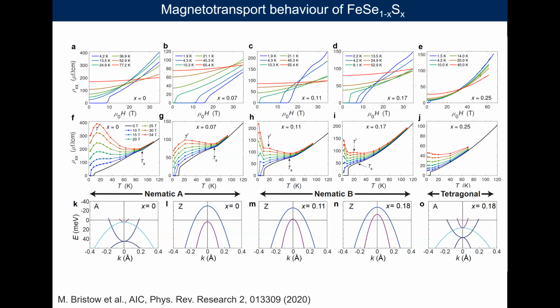So this system should be in the normal state by now. You know, we are measuring here in 34 Tesla. Upper critical field of this material is about 16 Tesla. So it's a factor 2 higher than upper critical field, and it has the signature in this regime. So all the resistivity dropped down below the expected superconducting transition. So surely this tells us something that we still don't understand.